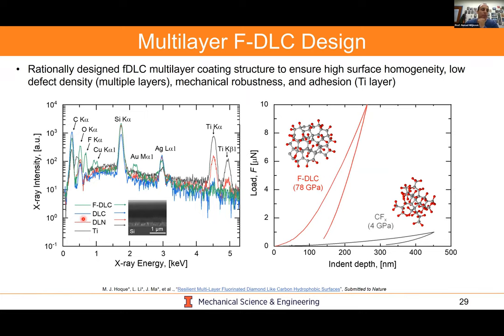What you're seeing here is EDS spectra of our coating as a function of the X-ray energy. And you could see the different elemental composition within the coating, depending on where you're looking. This is a four-layer formulation. There is the substrate, the silicon. There is a layer of titanium, which is the adhesion layer to hold everything down. There is a formulation of DLN and DLC, DLN having a high silicon content to give it high thermal stability. This coating can actually hold up to 300 degrees Celsius.